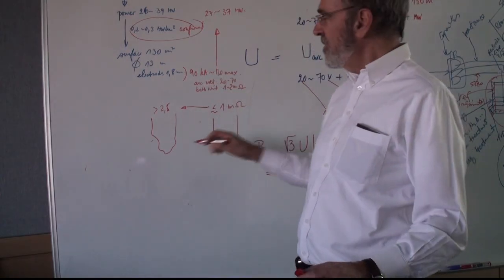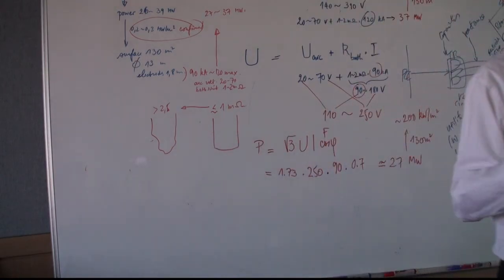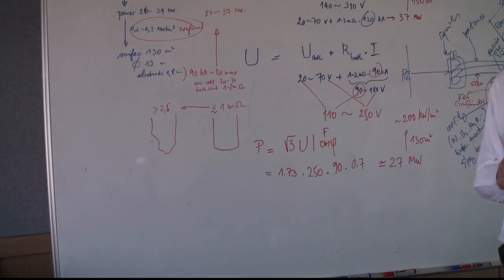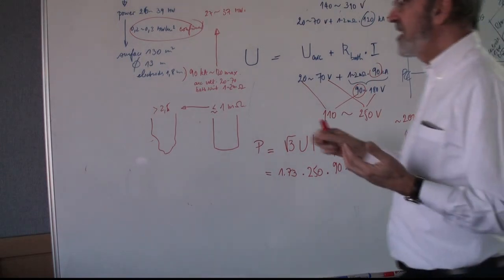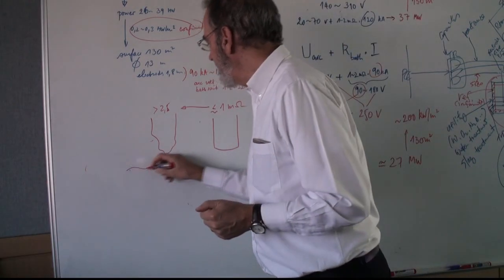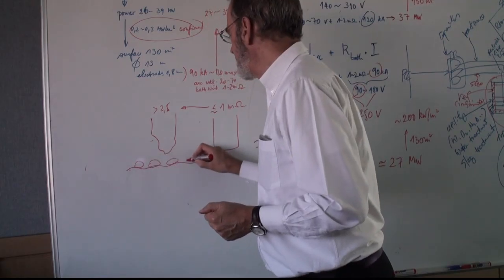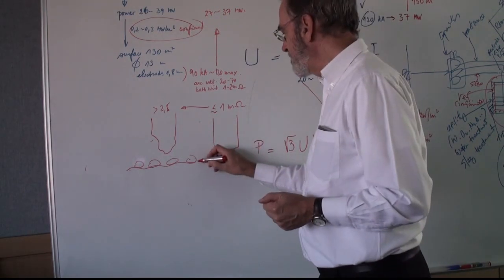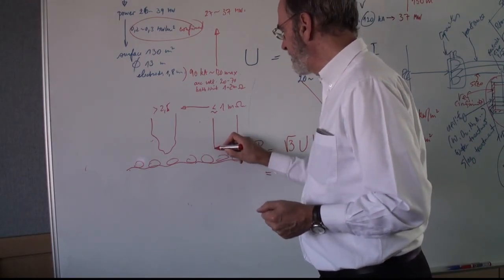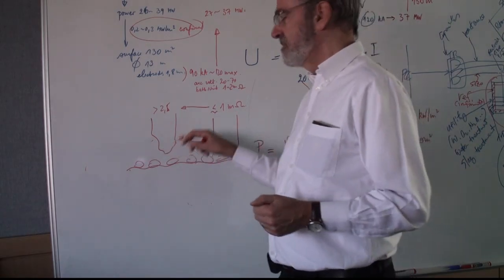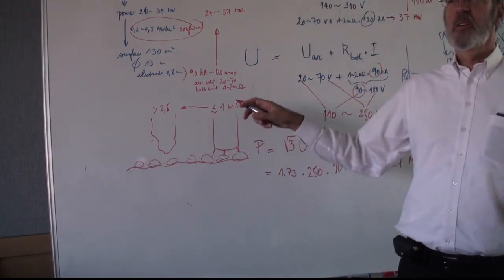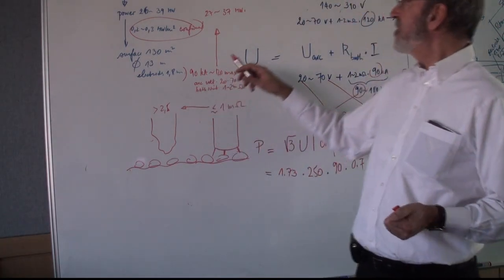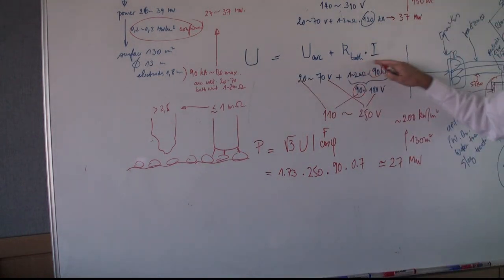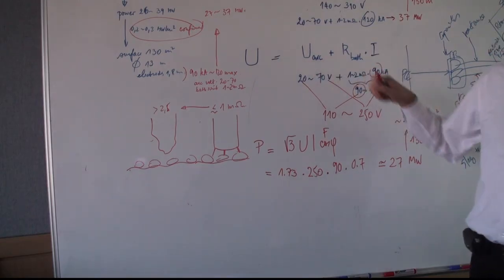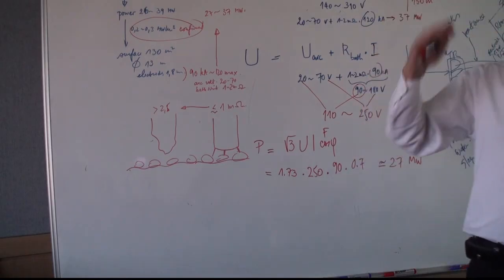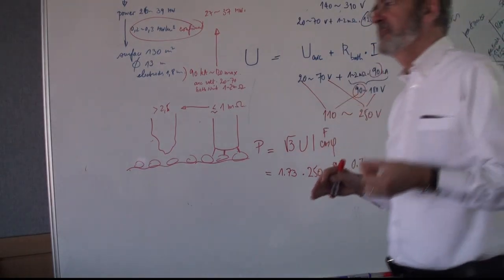But at the same moment, when you have this, you have less arc voltage, because you understand that these are not good conditions. If you have coke here, it's not good conditions to form arcs. This is good. This is not good at all. So, in this case, you have a higher resistance. So the second term is increased, but this term is lower. So there is a kind of self-balancing effect.